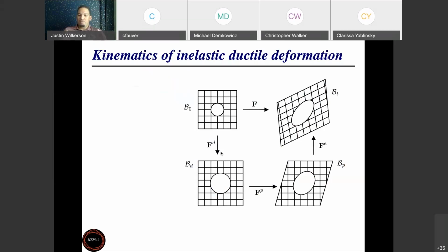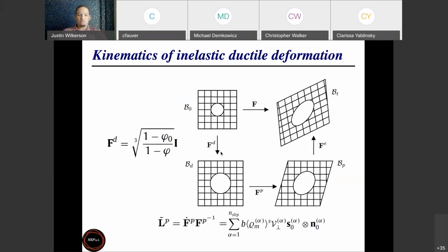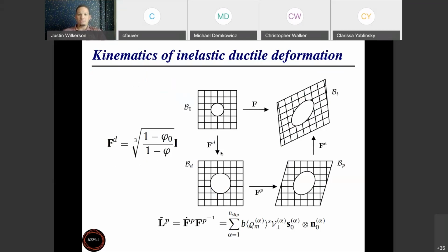That's going to affect all of this elastic volumetric strain energy that you had stored up in the material. You're going to relax the stress by converting that to inelastic strain. And that's not always accounted for as properly as it should be, but it's really, really important to account for this in dynamic fracture of materials.